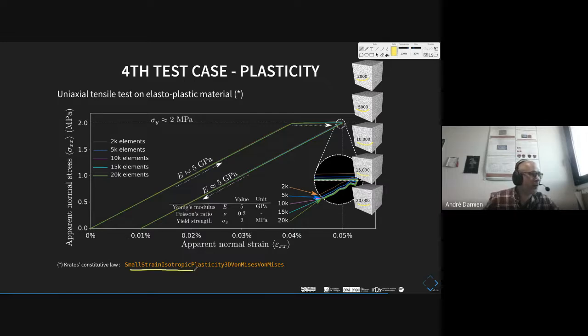So here we introduce a perfect plastic material with this Kratos constitutive law, and we get this apparent answer because this sample was simply submitted to tensile tests. So it's quite good results. Again, here you get the input parameters. Here we introduce only yield strength, and we obtain this yield strength. The results look good to me.